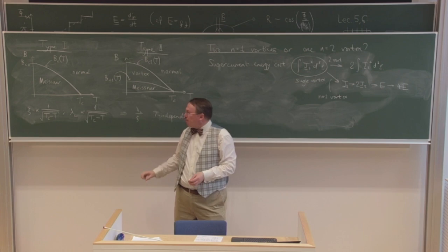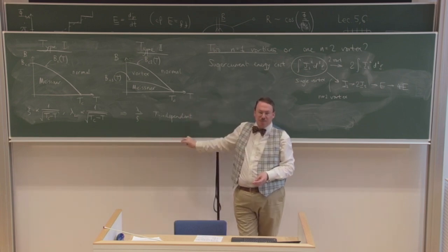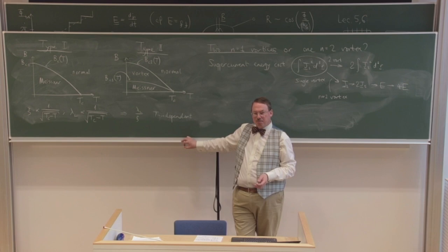And the other, even more spectacular point of those demonstrations is that you've got the superconductor levitating over the magnet, turn it upside down and it's still there. Because there's too much energy to try and move the vortices that you created. If you tried to do it in the Meissner state, you'd run into all these problems; you'd have to do something with your magnetic fields to create the potential minimum that it sat in to sit there and be observed. Otherwise it can just bounce off. It would be very unstable, just flying off. The demos work because of vortices.